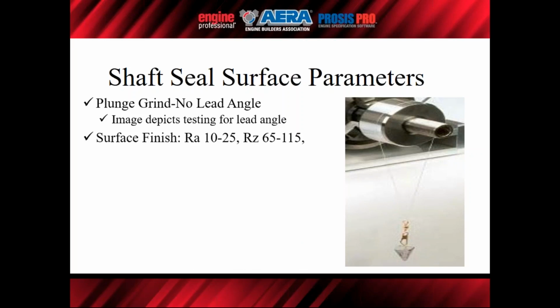Surface finish parameters. Typically, most of us are using Ra, but there are also parameters for Rz. Rz is a 10-point peak count, so this is actually a very good surface parameter for gasketing and so forth as well. And you see Rpk, that is peaks above the mean line, and it's 20 to 50. All these values I listed today in micro inches rather than do the conversions.